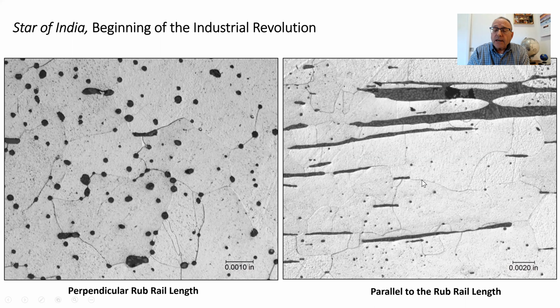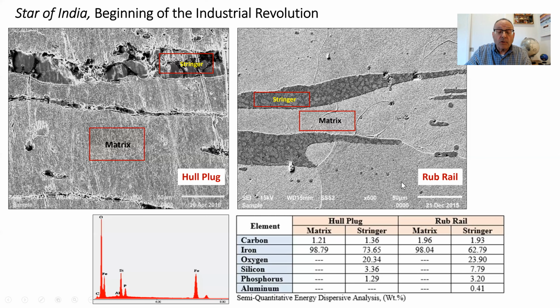So the first thing we did is we took this sample and we took the other sample and we put them in the scanning electron microscope. And the reason we did this is we wanted to do a localized, or what we call a spot analysis, of the matrix of the material and these stringers. And what you do is when you look at it in a scanning electron microscope, you're bombarding it with electrons, and from that, you get a spectra like this down here with iron peaks and silicon peaks and oxygen peaks, and we can run it through a computer analog and it'll give you an elemental analysis, semi-quantitative, so it's approximately what the chemistry is or what the percentage of elements are that we see.